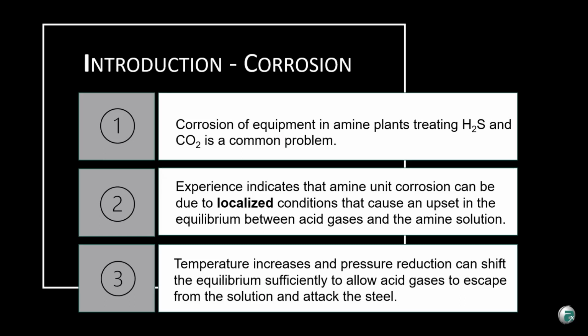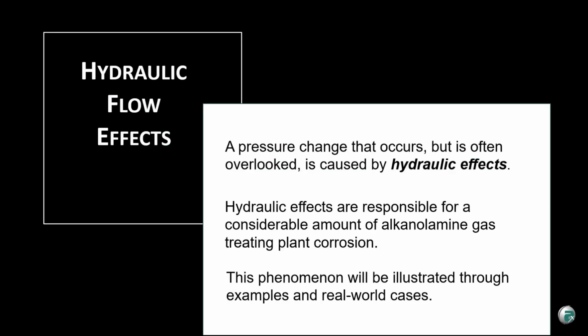Experience indicates that rather than being a problem throughout the entire system, corrosion in amine systems tends to be highly localized. One of the reasons for localized corrosion is the release of acid gases from that circulating amine solution. Both a temperature increase and a pressure reduction can shift the equilibrium sufficiently to allow acid gases to escape from the solution, and this escaped acid gas has the potential to attack the steel, depending on the temperature and the location that this acid gas breakout occurs. One pressure change that occurs but is often overlooked is caused by hydraulic flow effects within the amine unit. Hydraulic flow effects can lead to liberation of acid gases, and depending on the location of the liberation can lead to aggressive corrosion within the system.